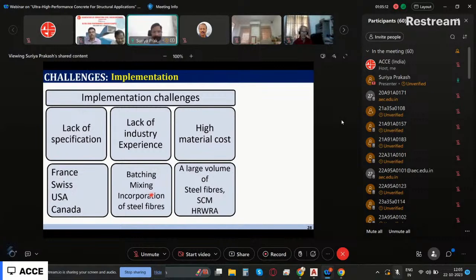I have to change the alloy composition. So the cost of the steel fiber that we are using is about 210, 220 rupees per kg. So again, cost is an issue. And we need a lot of good quality supplementary cementitious material, and the admixture quantity is also going to be high.